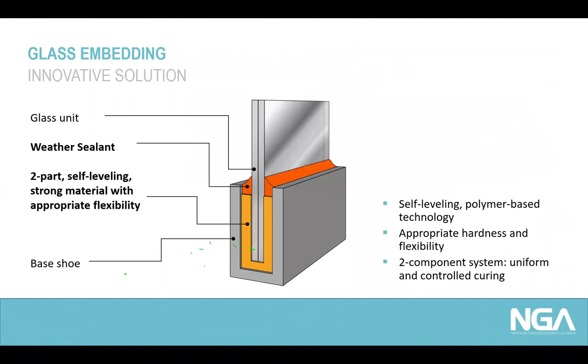process for the installers. So we have our aluminium base shoe. The laminated glass unit is set into the base shoe and adjusted. Then the remaining gaps are fully filled with the two-part self-leveling polymer-based material, strong material with appropriate flexibility to not produce any concentrated stress in the glass unit. And then after curing of that two-part material, it's covered with a cap joint, with a weather sealant to guide any kind of liquid water away from the base shoe, and to provide also the required color match for every specific project. So we have a self-leveling polymer-based technology with appropriate hardness and flexibility, and the two-component system for uniform, controlled, and fast curing.